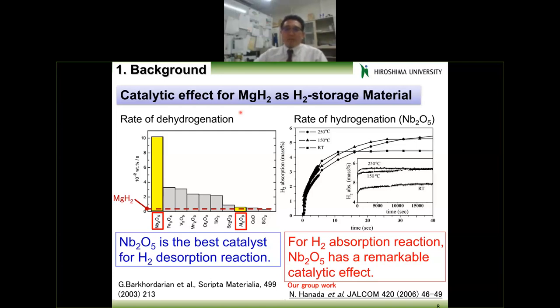But one German group focused on a catalyst using oxide. And they reported that niobium oxide acts as quite a good catalyst for magnesium. Of course, they reported this quite drastic kinetic improvement, but they didn't focus on the hydrogen absorption properties. But afterwards, we focused on this material for hydrogen absorption. And for the first time, we realized hydrogen absorption at room temperature. Usually this takes an hour scale or so, at 300 degrees or more. But in our report, at room temperature, we succeeded in hydrogen absorption within several seconds. It's quite a drastic improvement. So that is the starting point of our magnesium hydride work.